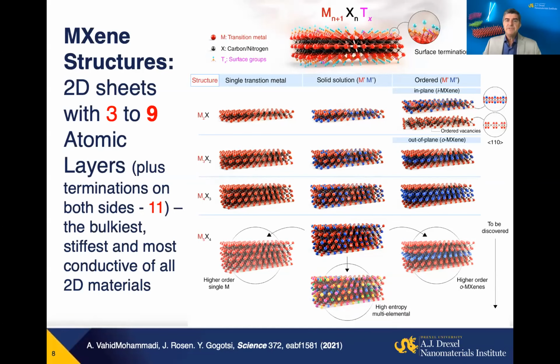We can make materials with in-plane ordering, where you have alternating atomic columns of elements on the surface. And if you remove one of them, for example from moly scandium carbide, you remove scandium, you end up with materials where you have monatomic vacancy layers going through the structure and making ridges on the surface here. Or we can make a structure with one element, for example moly, on the surface and another transition metal in the middle, kind of atomic sandwich structures here. And I'm sure this is not the end. So we basically push it to atomistic engineering of two-dimensional materials.